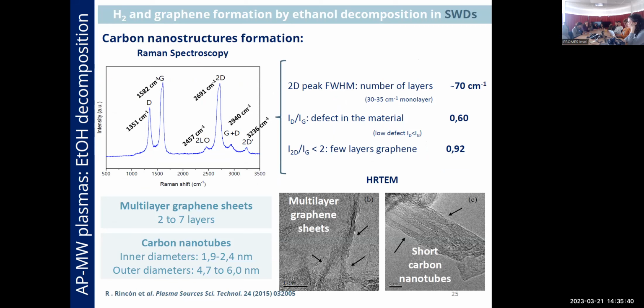So we did some analysis of this material. First, we checked its properties by Raman spectroscopy. Here you can see the Raman spectrum of the material. We can observe the 2D and G bands, which always appear in graphene and graphene-based materials. Actually, the other bands that are pointed out in the spectrum, D, 2LO, G plus D, and 2D plus, are related to defects in the material.